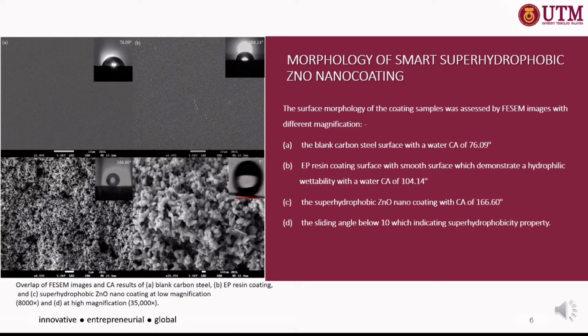EP coating is hydrophilic, proving its lack of low surface energy, whereas to achieve superhydrophobicity, the coating surface must demonstrate a low surface energy with the presence of surface roughness. So, the improvement in hydrophobicity of the zinc oxide surface over the EP film is attributed to the aggregation of zinc oxide nanoparticles. And D shows the sliding angles below 10 degrees, which indicate superhydrophobicity property.